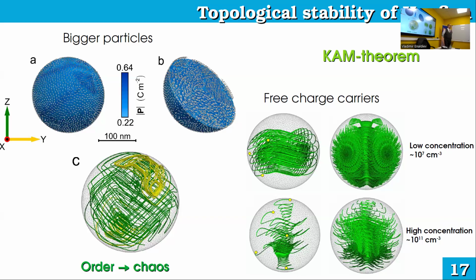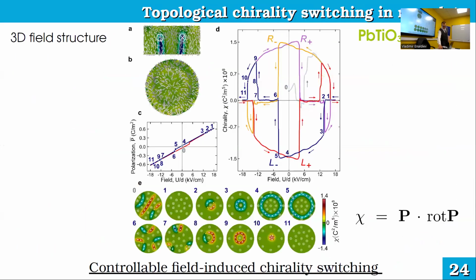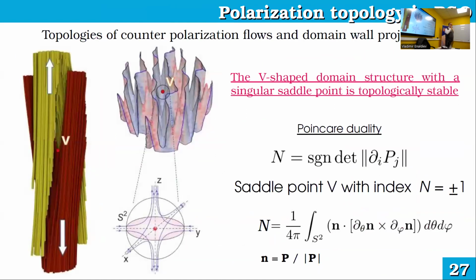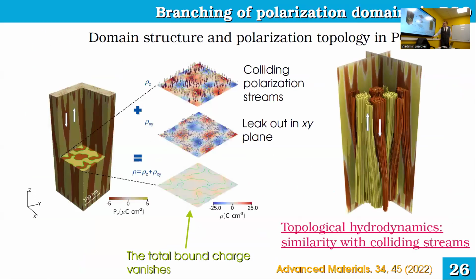I wonder about the continuity of the chirality flow. For the shear flow, you actually will have a laminar flow between these two kinds of propagating flow. So the velocity is there, at the interface of the up and down, so the chirality shall also be there or not. No. Basically, yes, there is maybe a very little discontinuity of polarization, but it's not that big to create a strong enough depolarization field. So as you can see, real charge is not exactly zero; it's just small.